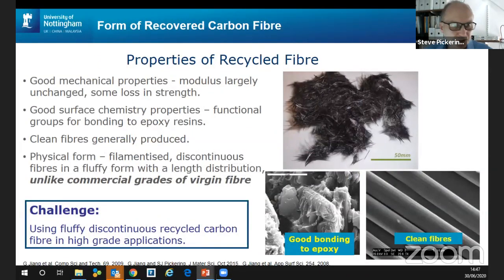So the key question is, what are the properties of these recycled or recovered fibers? Well, generally, it's been found in all these processes that you have good mechanical properties. The modulus, the stiffness of the fibers, is largely unchanged in all these processes. There is some loss of strength, particularly in the pyrolysis and fluidized bed processes where there is some oxygen there to produce the clean fibers. But nevertheless, this can be controlled, and the strength loss may be typically 10% or so.